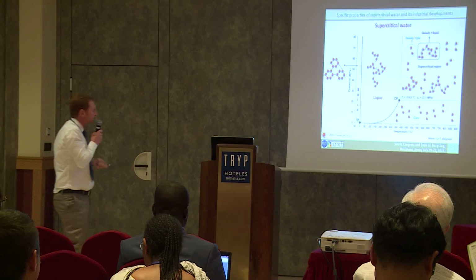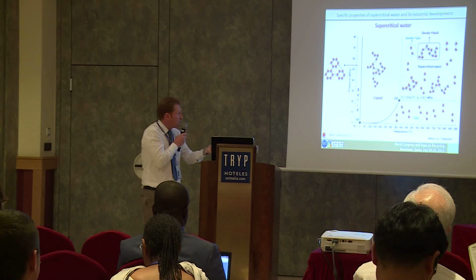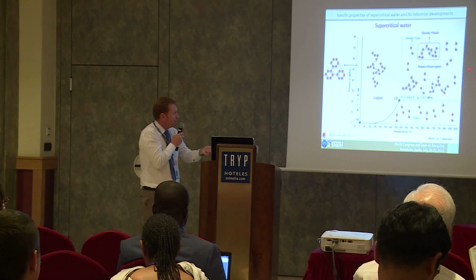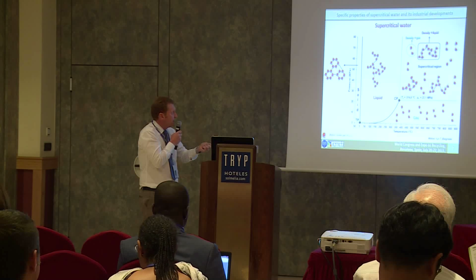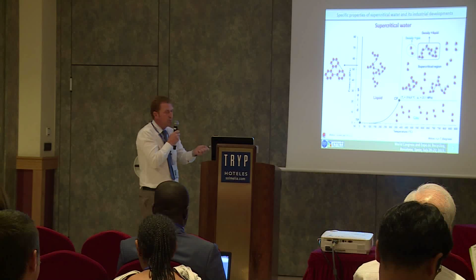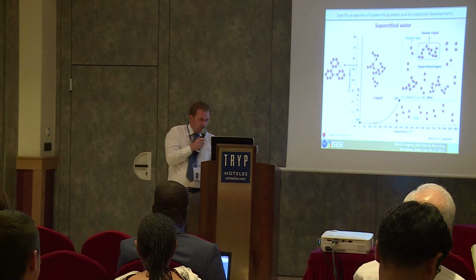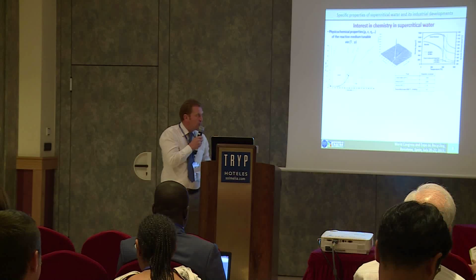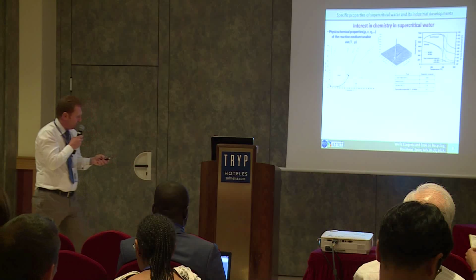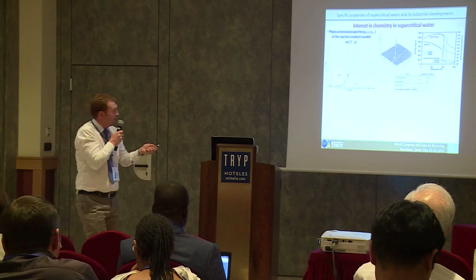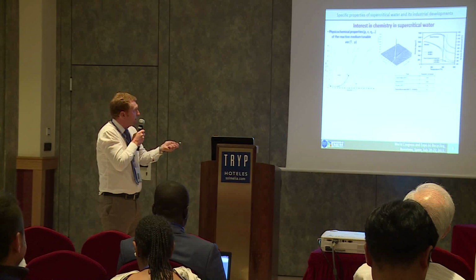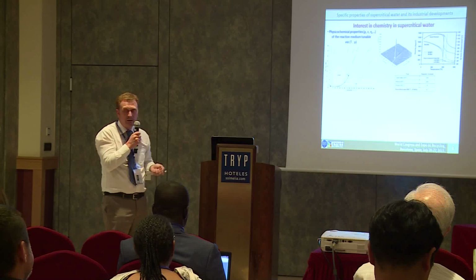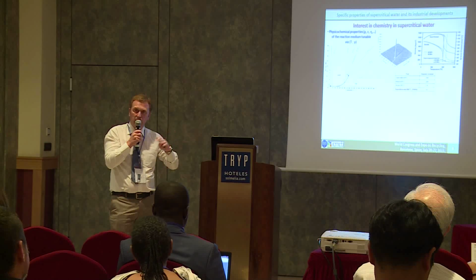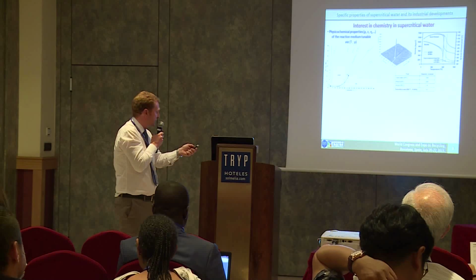is 221 bar. But as I told you, we see the possibility to change the properties, with some domains with liquid-like density and some domains with gas-like density, but we have also other interesting properties which can be used for chemistry. And this one is very interesting. You see, this is the evolution of the ionic product of water, the decomposition of water into H+ and OH-.